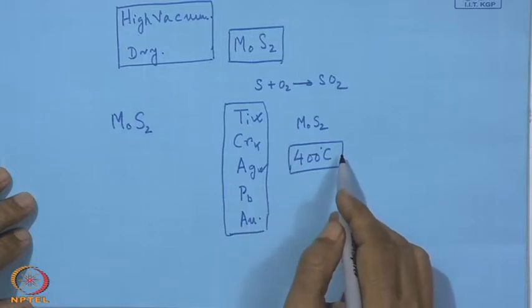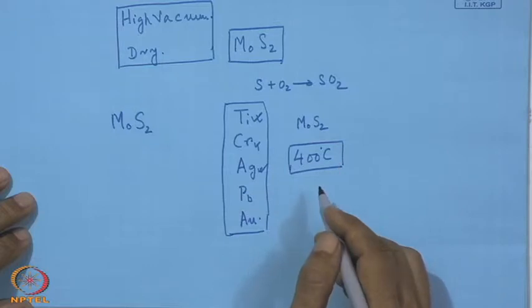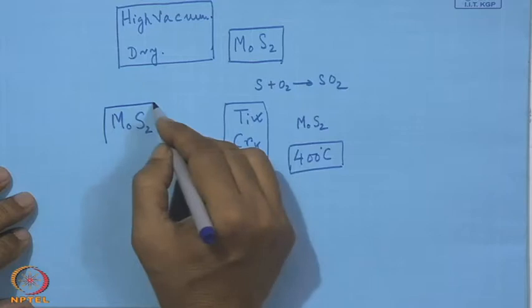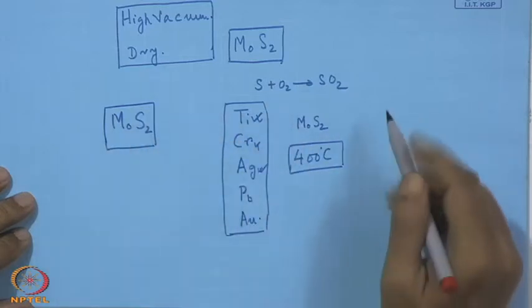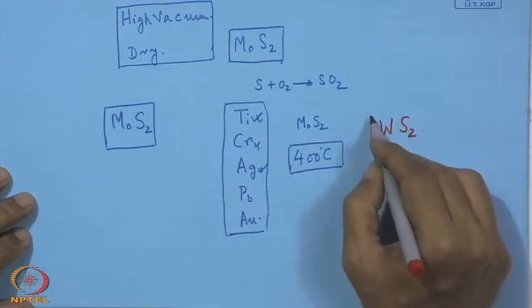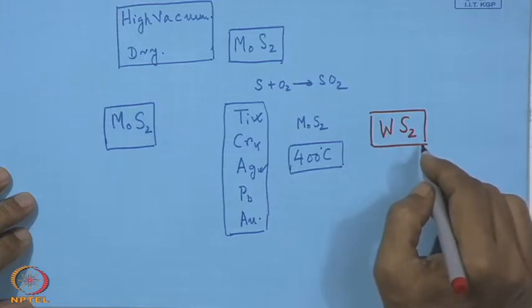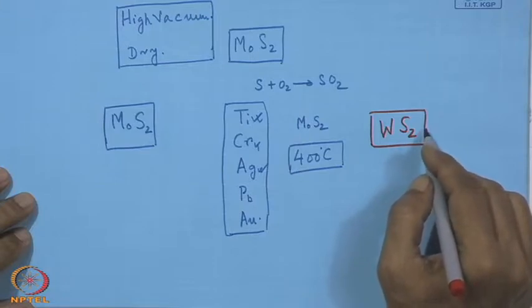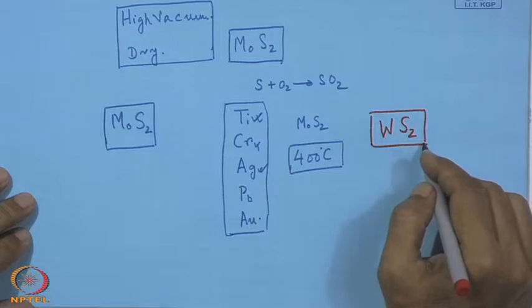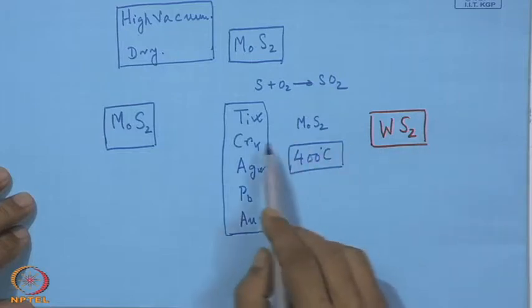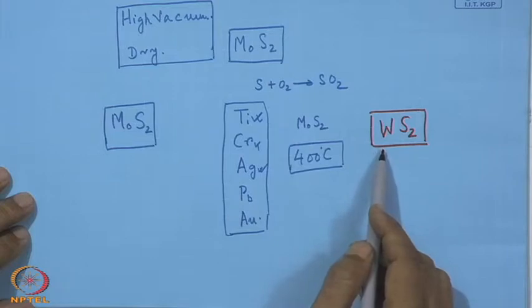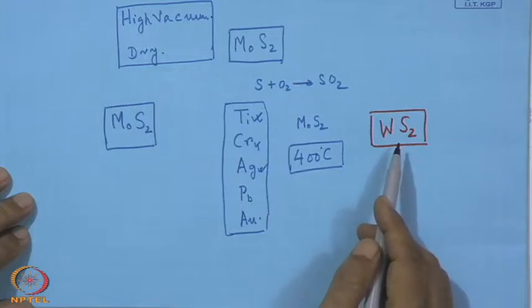However, the whole idea here is also to have titanium, chromium or silver with MoS2 to increase its capability to work at a higher temperature. And in this respect, we can mention here that we have on one side MoS2, but also we have WS2, a later addition, tungsten disulfide. So, this has a capability of holding its stability. It is chemically stable still up to 700 degrees centigrade. That can be also another good candidate, but it is to be also seen whether by adding such material we can also augment its property for various fields of application, where still we have to work with a higher temperature or with a higher level of humidity.